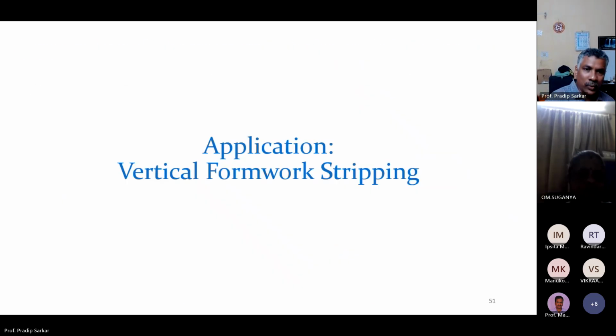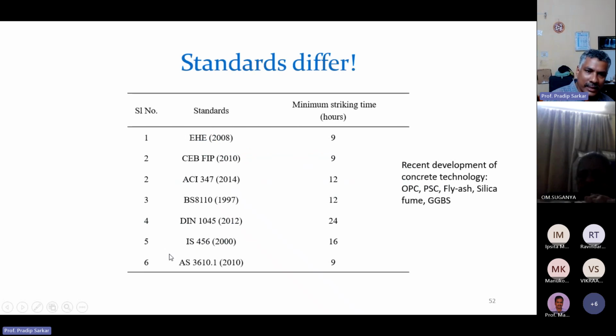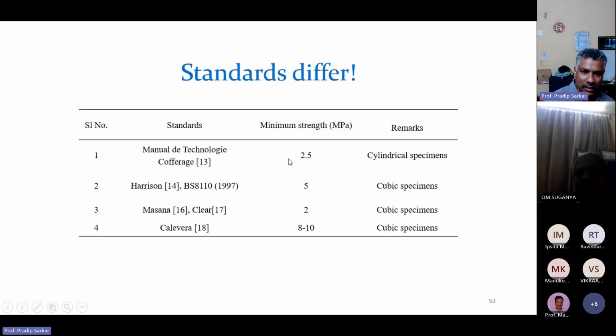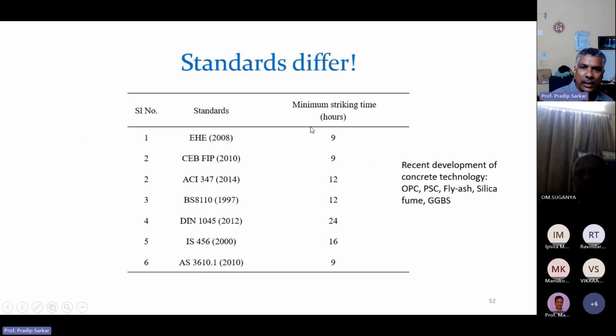Now we have used this system for precast formwork stripping. In the different international standards for precast formwork, the striking time of the formwork is given as from 9 hours to 24 hours, right? And these are all based on OPC cement concrete. But in recent developments of concrete technology, we are using PSC, fly ash, silica fume, GGBS, many things. So if we still stick to that time, sometimes there are problems we face at the construction site. These are the times given in the code.